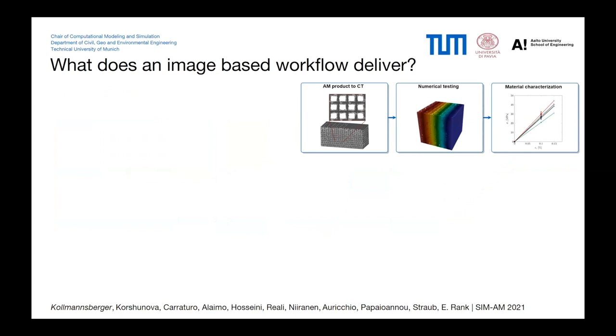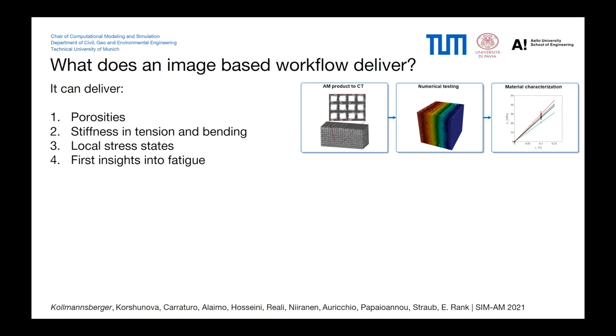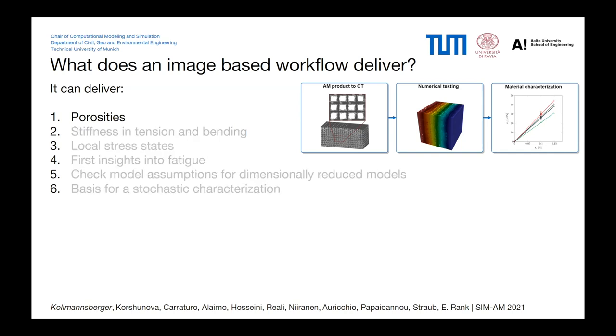What does such an image-based workflow deliver? What is it capable of? Well, it can deliver porosities, of course. It can deliver an estimate of stiffness in tension and bending. It can also deliver local stress states and also first insights into fatigue behavior of such structures. You can check model assumptions for dimensionally reduced models. These image-based analyses can also be a basis for stochastic characterization, as we'll show later on.